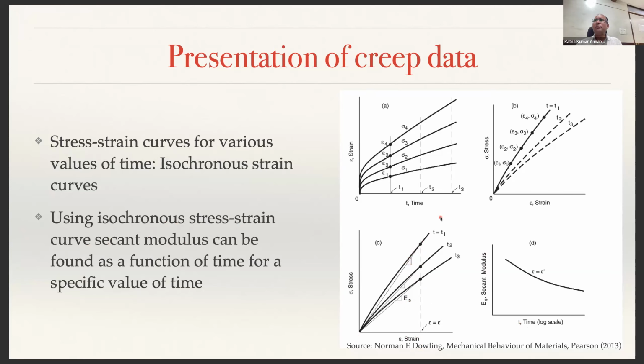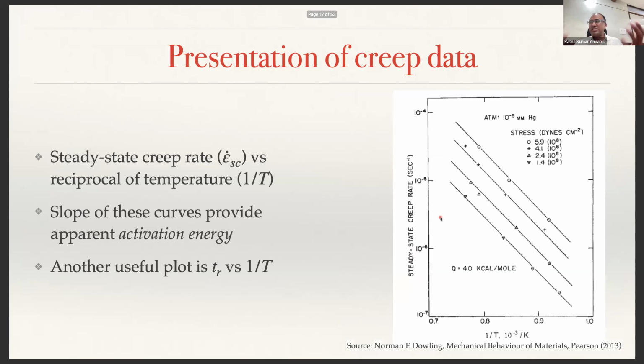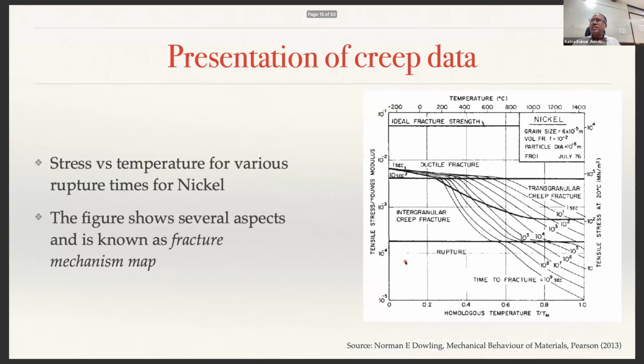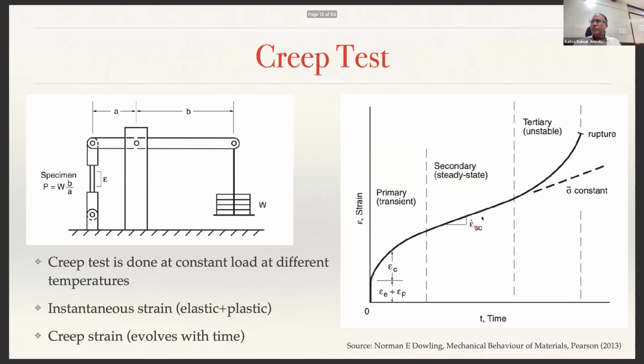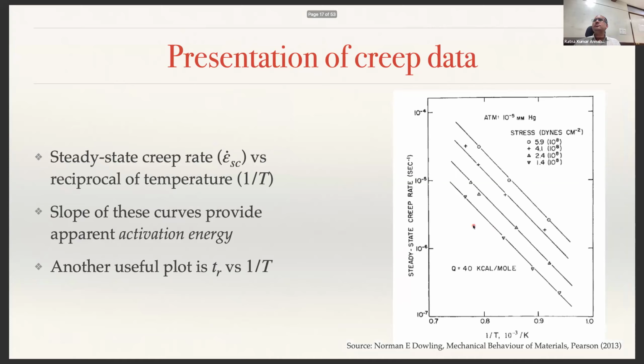The same data can be plotted in different ways to understand the creep mechanism in more detail. And there is another plot that people usually use for the presentation of creep data, the steady state creep rate. What do you mean by steady state creep rate? This epsilon dot SC. That value as a function of 1 over T, the temperature at which you are operating, and that again will be provided for different stress values.